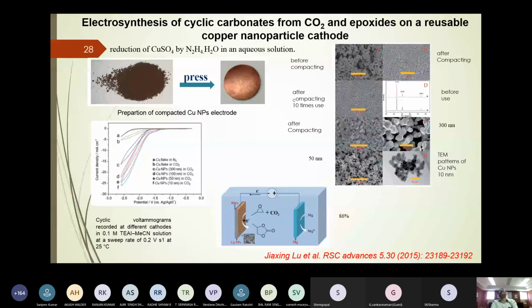synthesis of cyclic carbonates using copper nanoparticles, where they synthesize copper nanoparticles by a chemical reaction using hydrazine. Followed by that, they made it into simple coins. SEM shows the various sizes of the copper nanoparticles. They are in the form of small cauliflower-like structures, before compacting, after compacting, before use, after use, and then TEM shows the small particles, in the size of 10 to 20 nanometers.